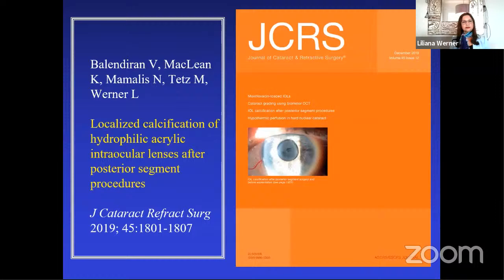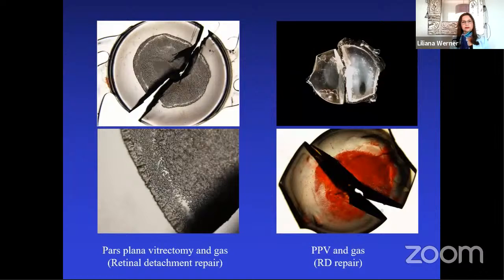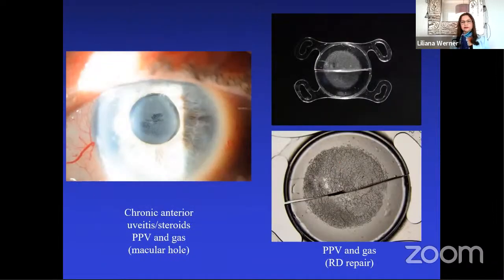Later, we observed the occurrence of the same pattern of localized calcification in hydrophilic acrylic lenses after surgeries and procedures performed in the posterior segment. Here, you can observe the same pattern of calcification with a round area of calcified deposits on the anterior surface and subsurface of the optic, corresponding to the opening of the capsulorhexis. This occurred after pars plana vitrectomy and gas tamponade. Again, at the capsulorhexis opening, there is direct contact between the IOL material and the aqueous humor.